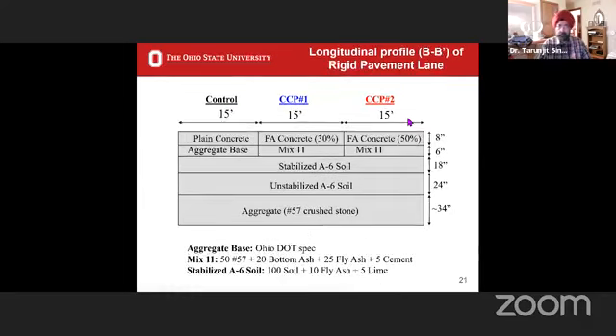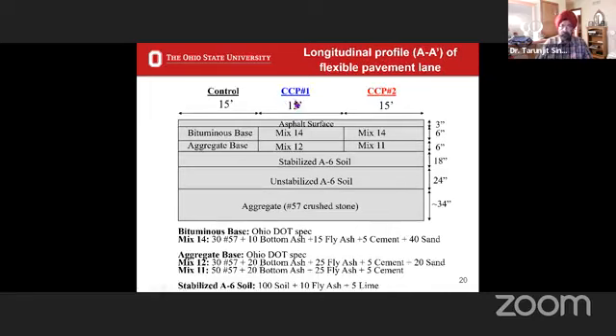And the one that we had for fly ash in terms of concrete, this is the plain concrete control section, with 30% replacement of cement with fly ash and 50% replacement. So as you go from black is control, CCP1 and CCP2, the red one has a greater amount of fly ash in CCP2 compared to CCP1.